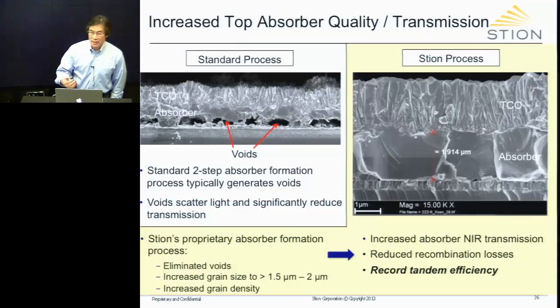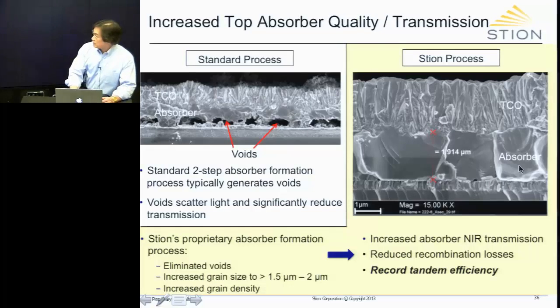However, on the other hand, if you're making the top absorber this way, these voids constitute a significant light loss problem. We have to get rid of these voids. If you have these voids there, you will never make it. Okay? So, as I mentioned, we have developed a different absorber formation process, and this is the SEM from that process. This is roughly a 2-micron thick film on top of a TCO, and what you see is that the grain sizes are enormous. They're on the order of 1.5 to 2 microns, even thicker, but the voids are completely gone. The increase in the transmission is dramatic, and I'm going to show it to you in the next slide. But this is an extremely important problem to solve if you're going to extract any useful efficiency from the bottom device. If you don't do this, then don't bother making a tandem.